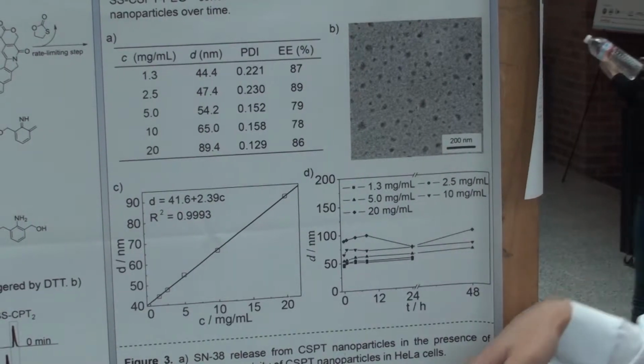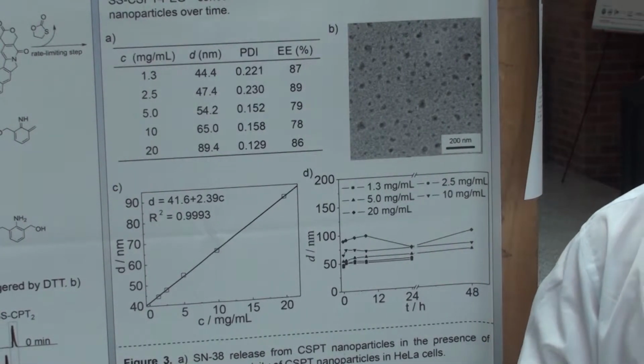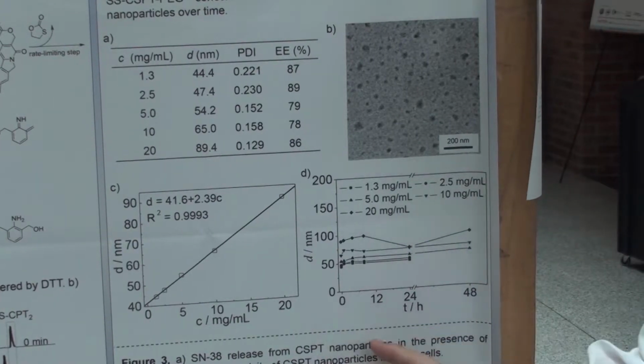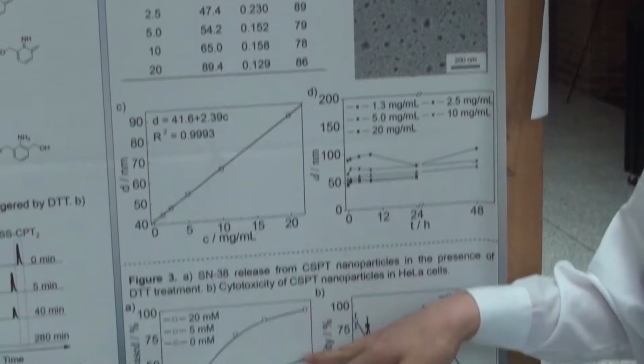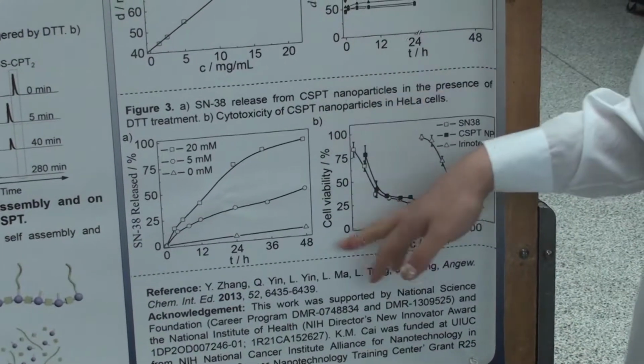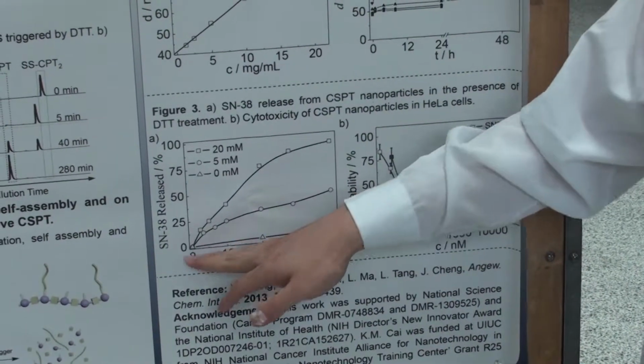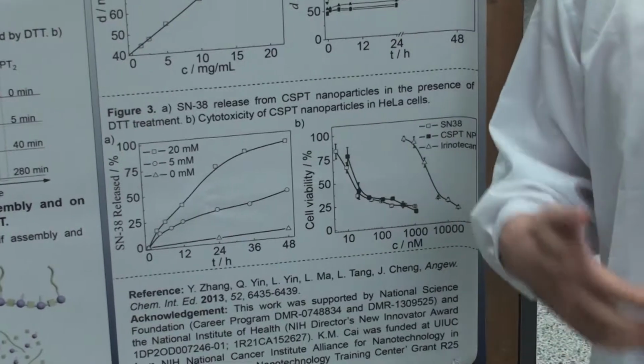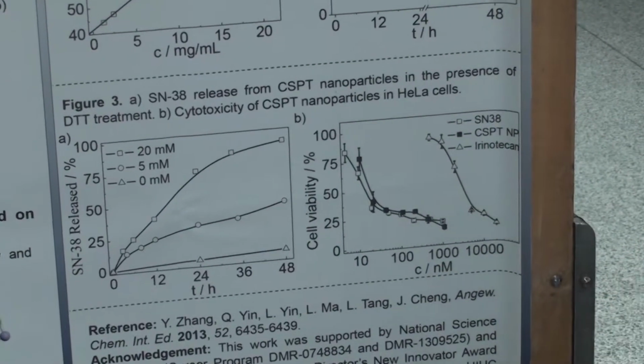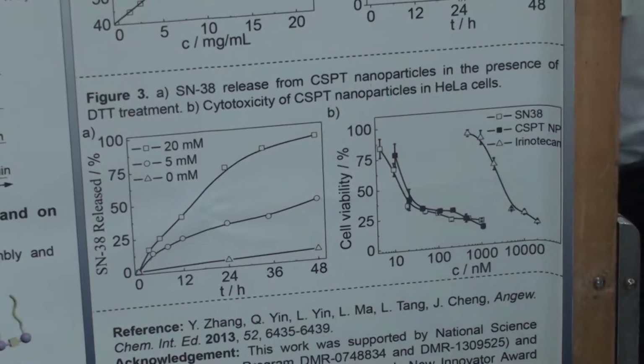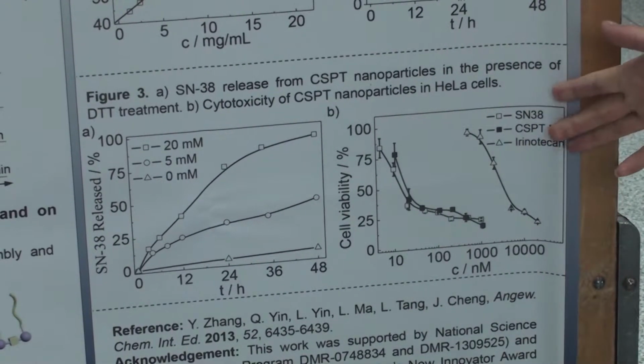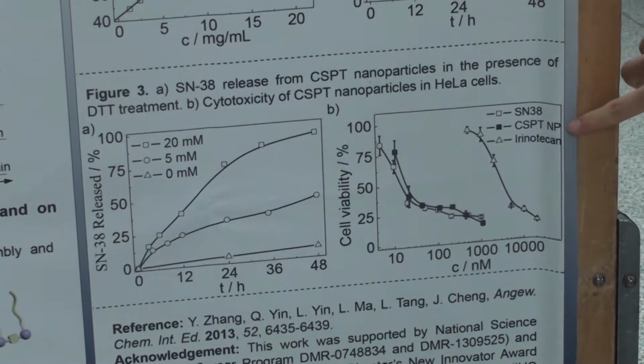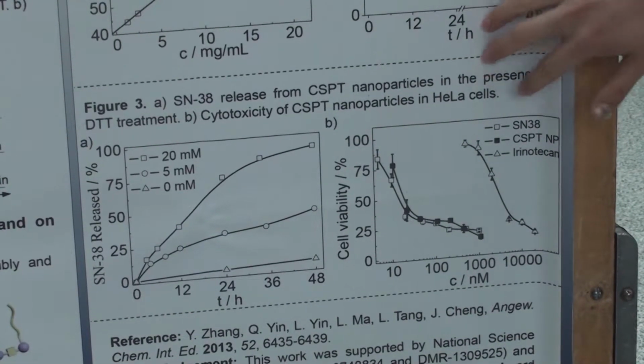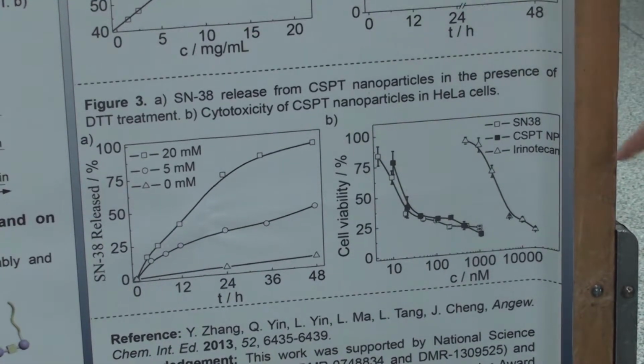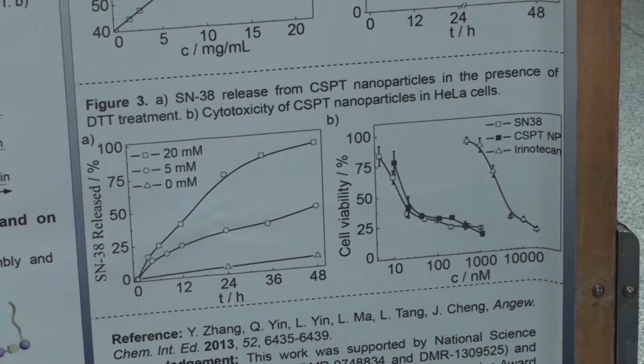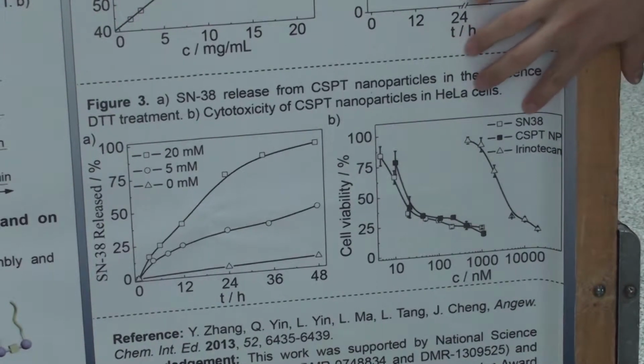And further work we did is to confirm the trigger-responsive property of our systems. Very interestingly, we can see a concentration-dependent release kinetics for our systems. And in the absence of triggers, the particle is very stable without releasing any of the drugs in the system. So we further did an in vitro assay to evaluate the anti-cancer effect of our systems. That is the MTT assay here. So we compare our nanoparticles with the drug that is conjugated to our polymer, and in clinical use, irinotecan, that is a derivative of the drug we use, SN38.